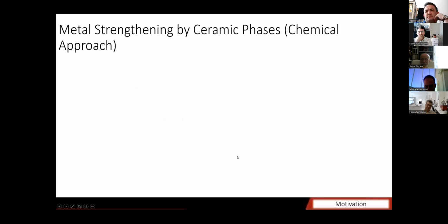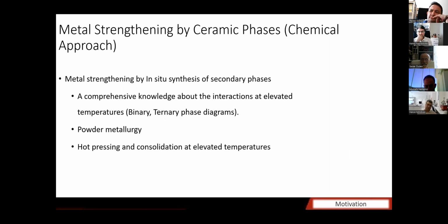We propose a chemical approach. In a chemical approach, what we can do is that you again use powder metallurgy, but you use it intentionally in such a way that you can have a thermodynamical interaction between the particles at elevated temperature. If you do that, then maybe there is a chance of changing the morphology and the size and also the distribution of the ceramic phases in the metal. So the metal matrix is reinforced by the ceramic phases instead of the ceramic particles.